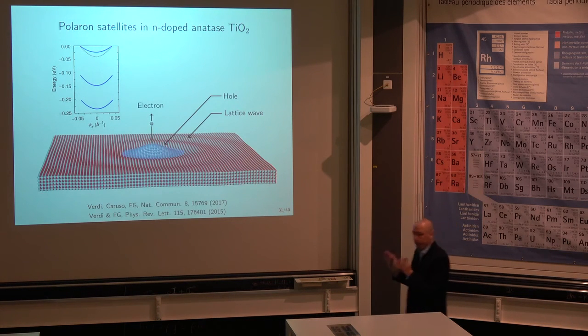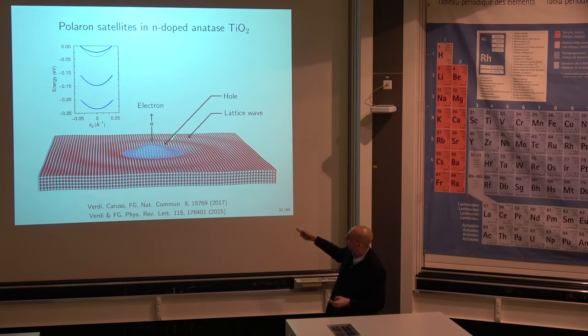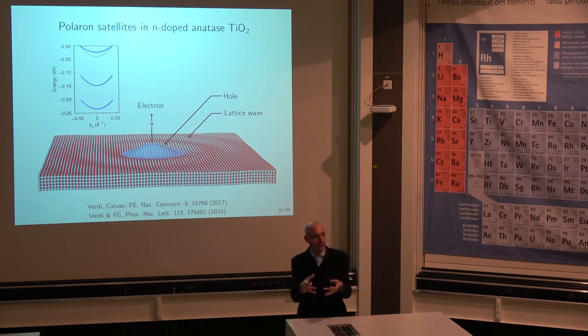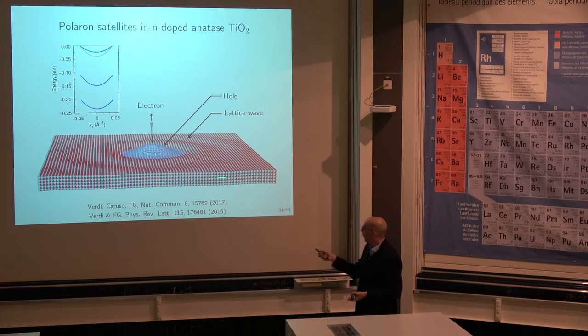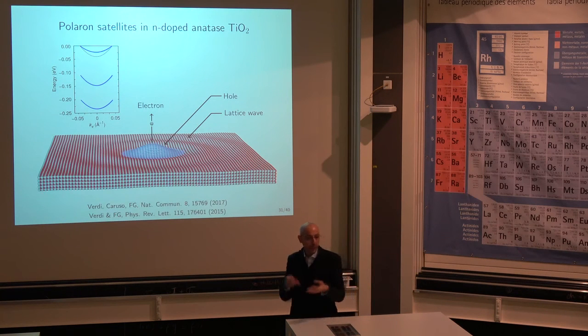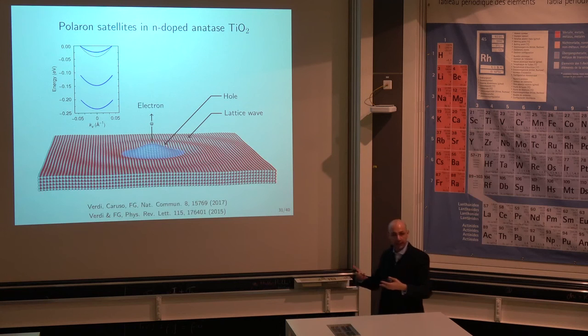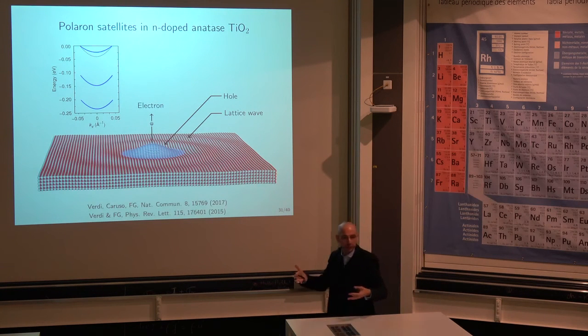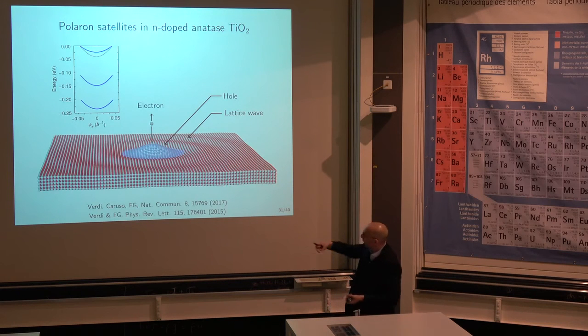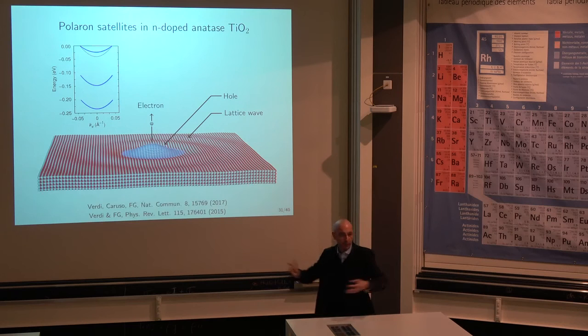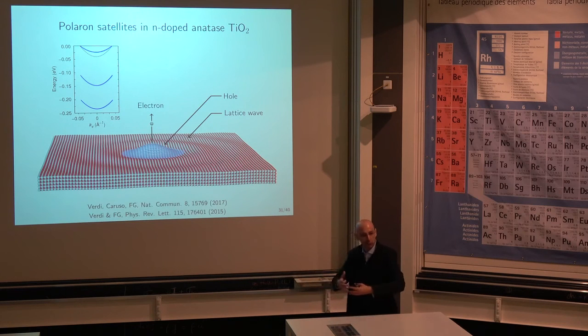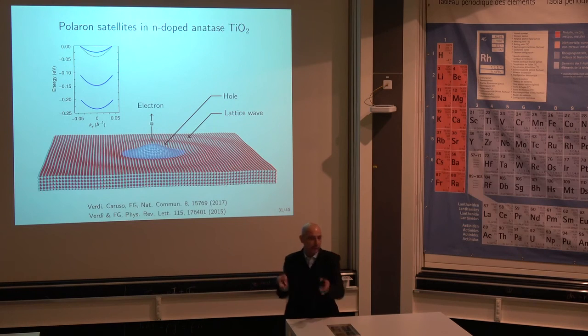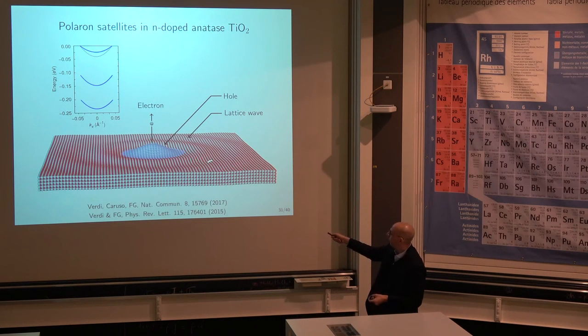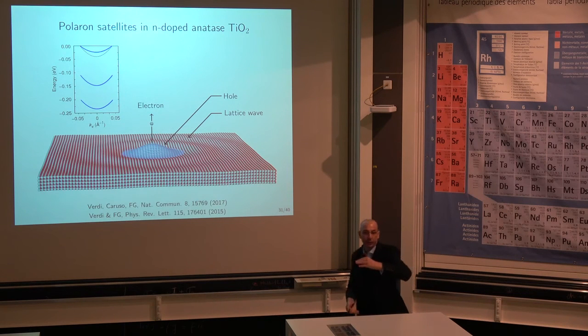That's just a cartoon, it's not an ab initio calculation, but basically you come with a photon, you extract an electron, and that creates a hole in your material. There is a puddle of positive charge. Titanium and oxygen are 4 plus and 2 minus respectively, so they're ions, and they feel an interaction with this charge, which is the hole, and they start responding. So there will be forces. In practice, it's as if you pinch a membrane and the lattice starts vibrating, with a wave propagating outward from this extracted electron. This is what we call a phonon. It's not a phonon in the sense of a periodic object, but a linear combination of phonons. The amplitude of this oscillation gives you the number of phonons that you have excited: the more phonons you excite, the higher the amplitude. That's the mechanism that is happening.